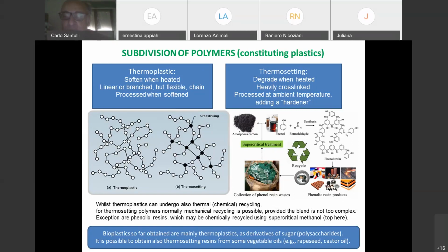but if processed at supercritical temperature, so you may remember that supercritical temperature means that they are not able to liquefy anymore. If we process phenols with supercritical methanol, in an atmosphere of supercritical methanol, we are able to transform them to carbon. Just carbon to make active carbons, electrodes, and so on. This is more a research consideration than an operational consideration.